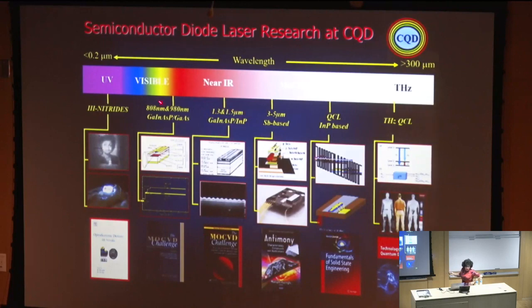For the 1.5 micron, again, it was liquid phase epitaxy, and everybody was using it, but the problem was how to have the DFB and really the quantum structure. So again, I developed the MOCVD and demonstrated it. That really changed telecommunication in the 1980s, after my PhD, up to 1990. Everything is in my book, MOCVD Challenge Volume 1, now in the second edition. This result is the first indium phosphide, gallium indium arsenide superlattice that really changed everything that I'm giving now for the infrared and the terahertz lasers.